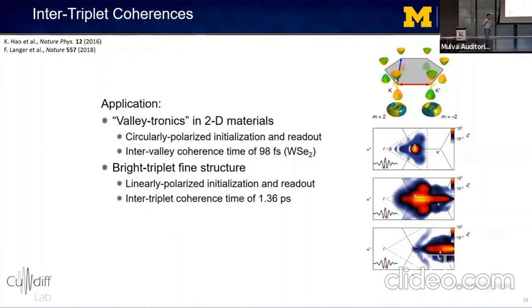And to motivate a possible application of these intertriplet coherences, I'd like to draw an analogy to valleytronics in 2D materials, where circularly polarized valleys in the band structure are used for quantum information. And even though the dephasing times in these 2D materials are quite short, it was actually shown that you could transfer exciton polarization from one valley to another with a terahertz pulse within a single optical cycle. So one could imagine performing similar operations on a perovskite nanocrystal with linear instead of circularly polarized initialization and readout. And if we compare the inter-valley coherence time of, say, tungsten diselenide of 98 femtoseconds to the intertriplet coherence time of 1.36 picoseconds, our intertriplet coherence time compares very favorably.